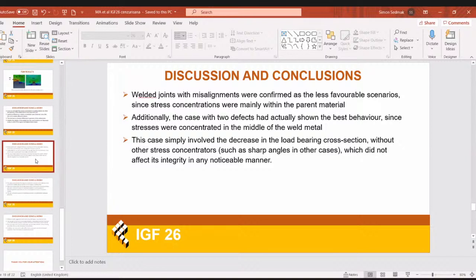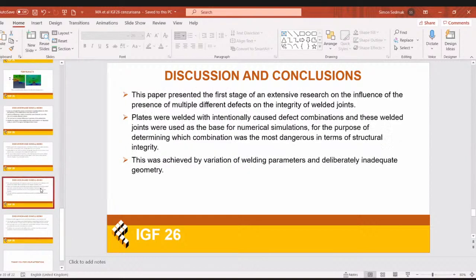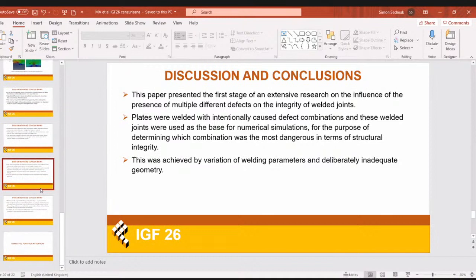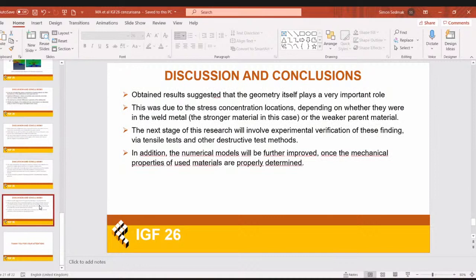Now, this was a couple of months ago, and in the meantime, a lot of things have happened. The models have been tested, and most of our assumptions were verified about the behavior in terms of stress concentration, except for some other models where we got a bit different results and concluded that we need some more detailed tests like macrofractography to determine what was the cause. We already established that, but that will be for some other opportunity. And now we're going to be doing the same with a slightly different material, while also making the similar combinations of defects. Actually, they are being welded and tested as we speak now.